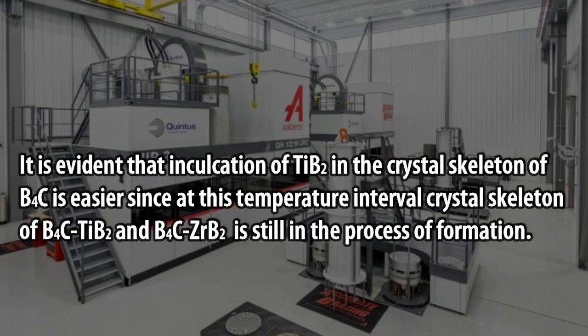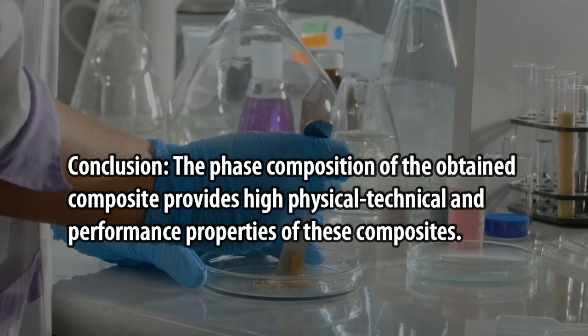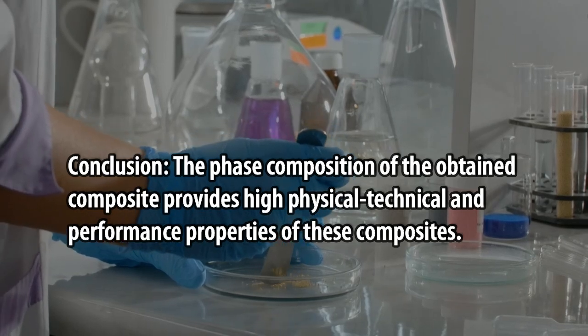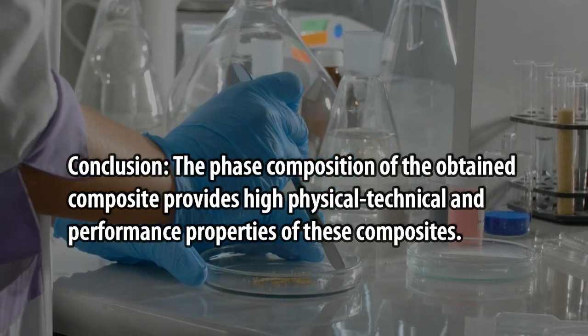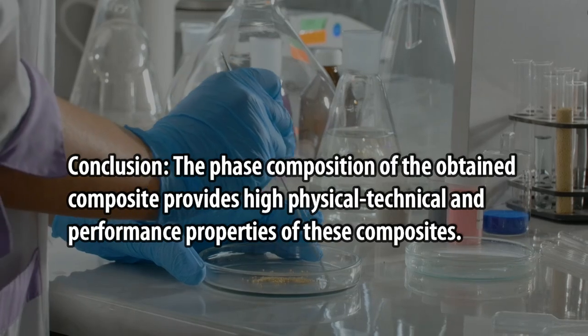It is evident that inculcation of titanium diboride in the crystal skeleton of boron carbide is easier, since at this temperature interval the crystal skeleton of boron carbide titanium diboride and boron carbide zirconium diboride is still in the process of formation. Conclusion. The phase composition of the obtained composite provides high physical, technical, and performance properties of these composites.